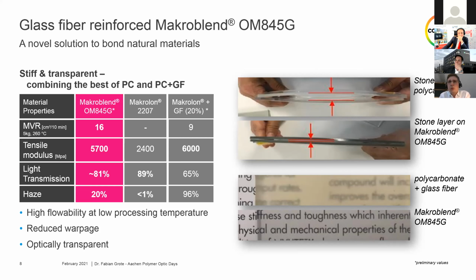However, we were able to overcome this issue to have a glass fiber filled product, which is extremely tough with a tensile modulus very comparable to standard glass fiber filled grades. However, it still offers you the transparency you need for these natural surfaces to be integrated into applications, with huge benefits in terms of weight and functional integration. So that's one of the very first trends we are seeing, especially in the interior of mobility.